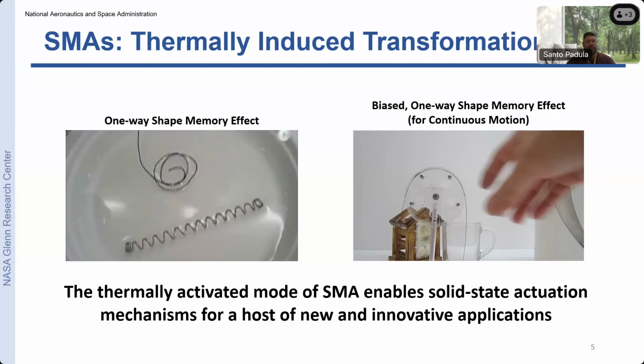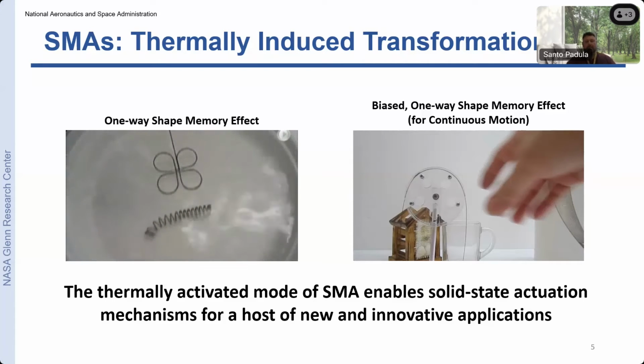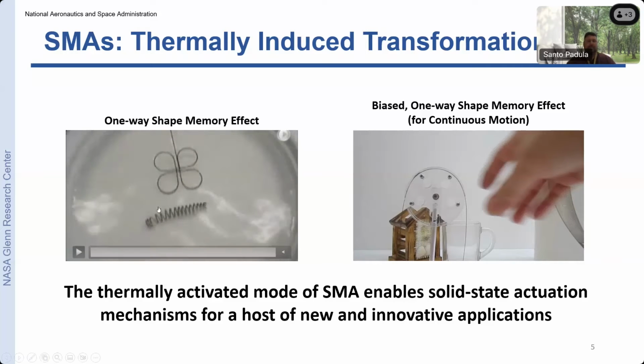So in this case, we're going to show the thermally induced transformation. And in the left-hand image here, you're going to see two structures that were already deformed to where they look like they've been plasticized. But as soon as we add heat to the system, we can actually revert those structures through large deformation fields to their original component shapes.